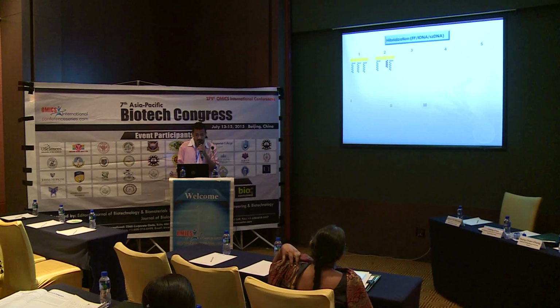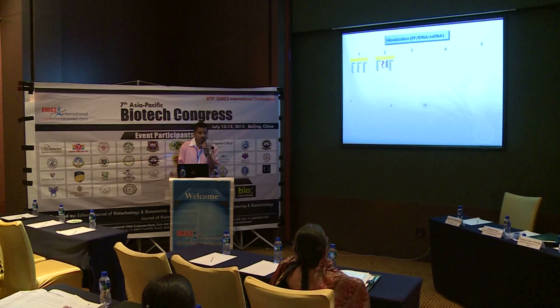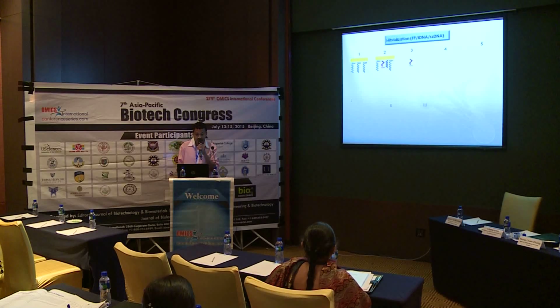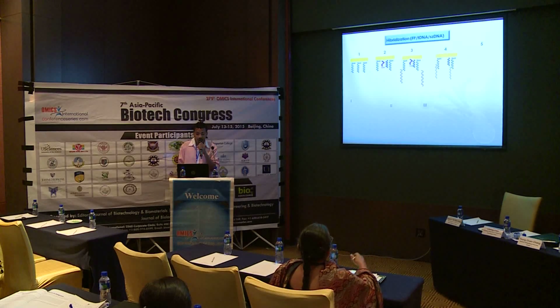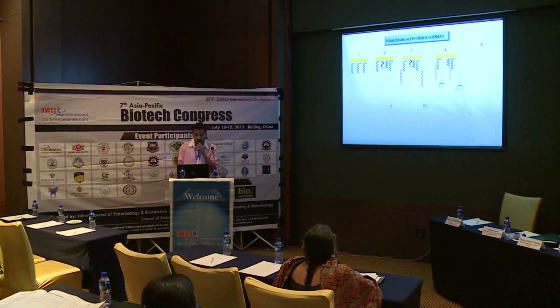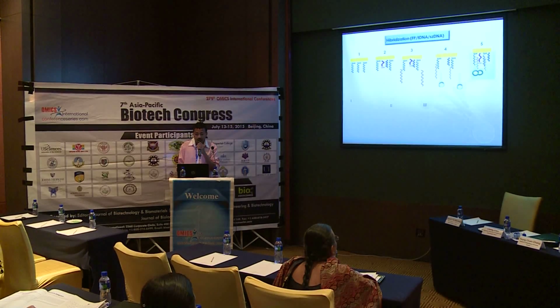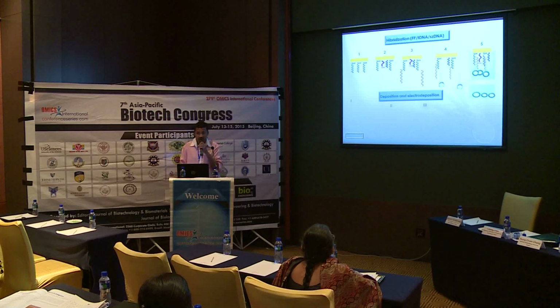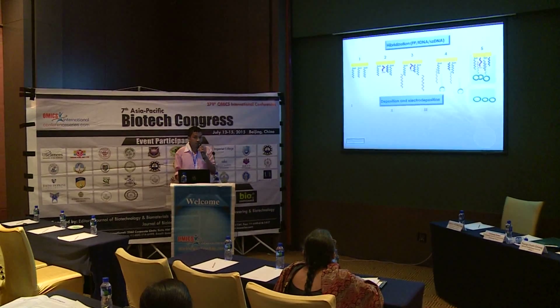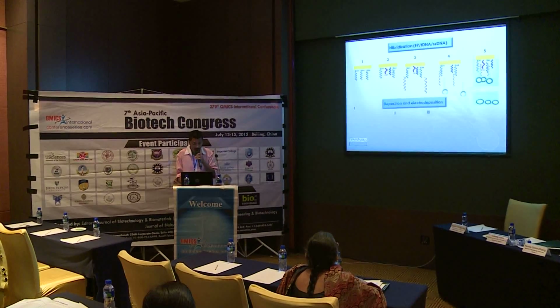This is the fixing; the yellow one means gold. So this is the fixing process. We do some chemical treatment. After that, we do some hybridization. The green one is our nanoparticles. So we put in nitric acid, and we do electrodeposition. This is also a critical step, because sometimes you can waste all your experiment. If you make a mistake in electrodeposition, you just get your baseline.